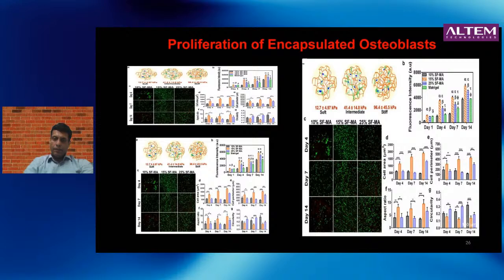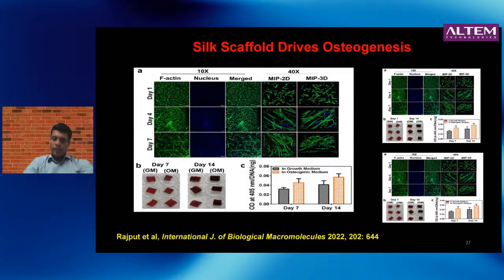And then when we looked at the ability of these pre-osteoblasts to turn into more mature osteoblasts and osteocytes, what we found is in that 15% gel, initially the cells are more compact, then they start spreading out a lot, and finally they become very spread out, much like osteocytes, and that happens spontaneously as you culture them from day 1 to 4 to 7 and so on.